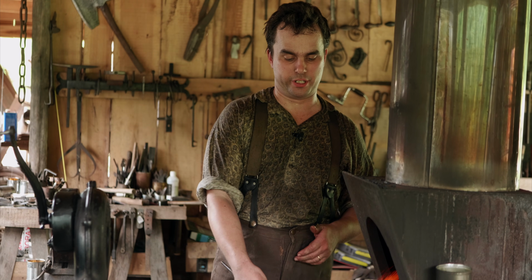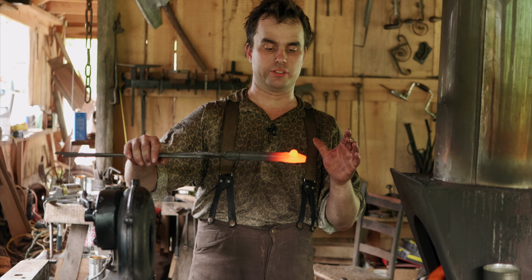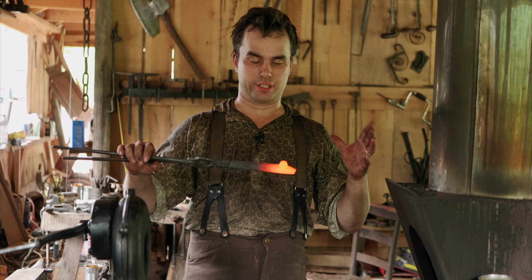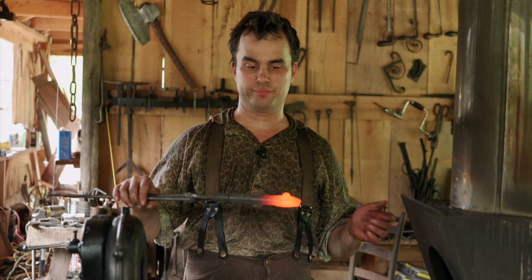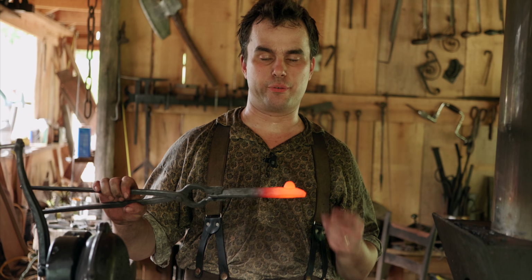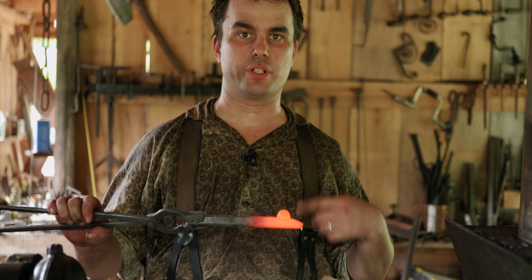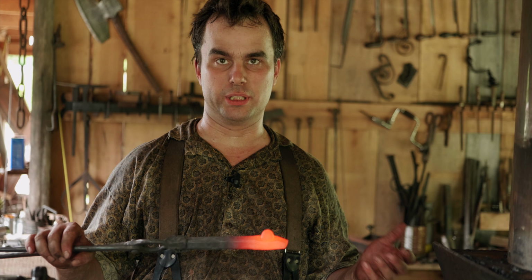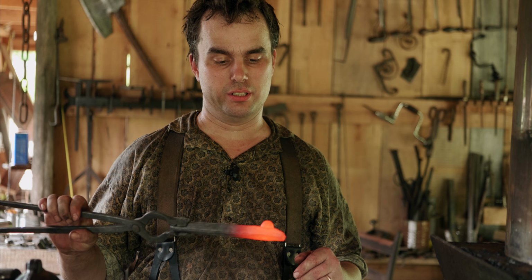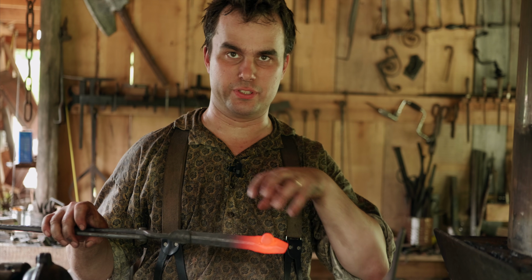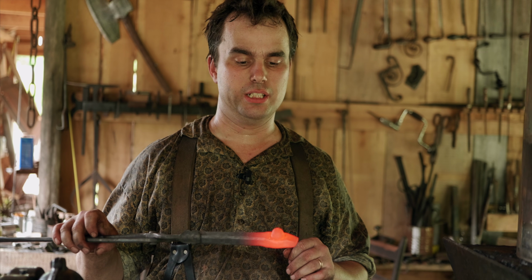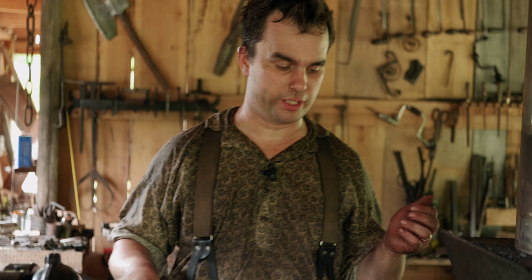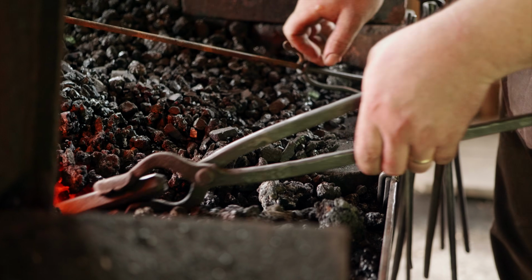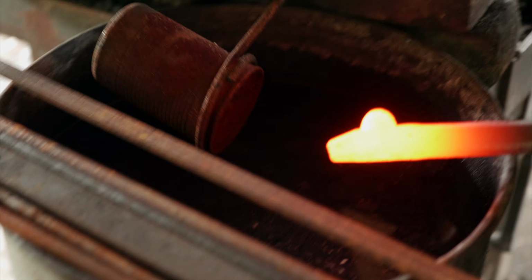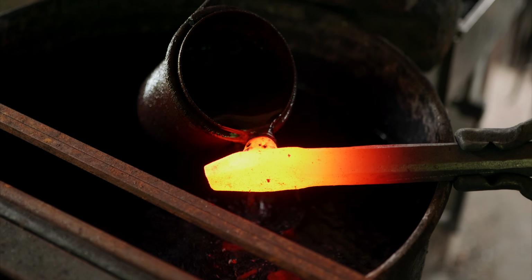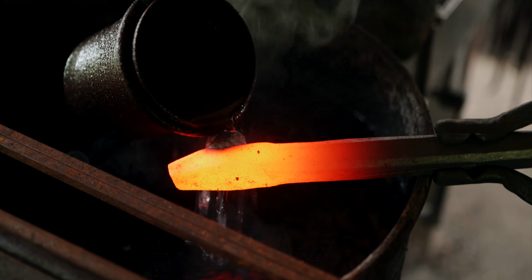So the first step in heat treatment is to heat the steel to the critical temperature for whatever carbon steel you're using, and then let it cool, air cool slowly 3 times. And each one of those cycles is called normalizing, thermocycling, and that relieves the stresses from forging that are in the steel. And then we'll reheat it to critical temperature and go for the quench to harden. Might be a better idea to use oil, but I'm going to use water. And we'll hope we don't get a crack.